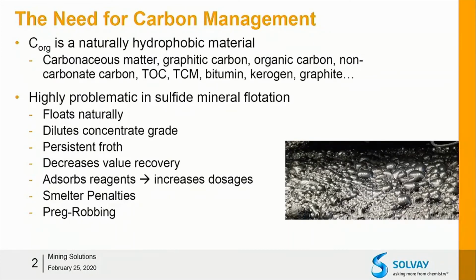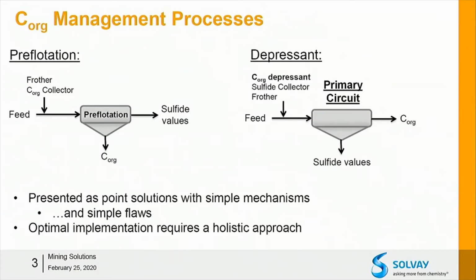Also, you tend to see very high reagent dosages when you're processing carbonaceous sulfide ores. It's because it's so hydrophobic, it adsorbs reagents onto the surface. And you do see some downstream penalties, smelter penalties. Preg robbing with carbonaceous gold ores is also really important to consider. And so with all these complex problems, both from a flotation standpoint, metallurgy standpoint, and downstream, it's quite interesting to see that the actual solutions that are proposed for carbon management tend to be presented as quite simple point solutions.